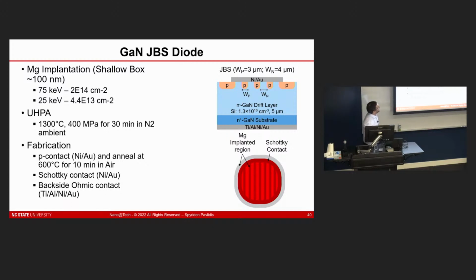And over COVID, we were really banging our heads up against the wall trying to figure out how to make good contacts to this material, right? So not just showing that we can deal with high electric fields and large reverse bias, but also forward bias characteristics being very good as well. And so what we did is we went ahead and wanted to demonstrate this through our target device, which is that JBS diode, where now you are creating a grid of implanted P regions. We mask the sample off with resist, basically send it off for implantation, strip the resist, and then send it off for ultra-high pressure annealing in Poland. You can see here that we've been tweaking our conditions a little bit with a lower pressure here, slightly lower times as well for anneal, and then we create these devices that have this kind of structure with these P stripes as well.